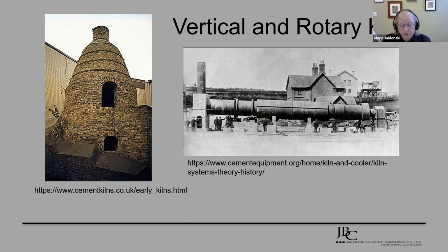The other findings were that it was dry tamp, or a very dry cement that was rammed. The beton was actually itself in excellent condition. There were no major durability issues. The problems that we had seen with the cracks were consistent basically with structural rather than material issues. And there was only minor evidence of internal cracking found in the samples that we had examined, and some of this cracking was also due to some freeze-thaw cycling. There was no natural cement in this cast stone. However, there was natural cement in the mortar used between the cast stone units.